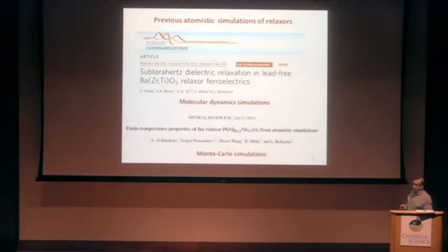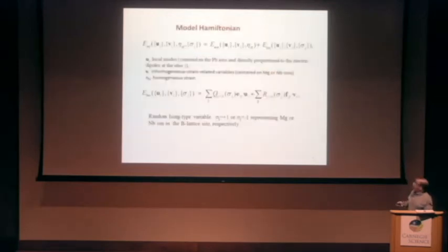We apply the same molecular dynamic technique for PMN. Of course, we need a different model Hamiltonian, and we use the Hamiltonian from this recently published paper for PMN, but they apply Monte Carlo simulations. But the Hamiltonian we used was exactly the same. And this is briefly the review of the approach. It's quite general. We have the Hamiltonian with two contributions, the average contribution, and the second one, local contribution, which is related to the disorder in the arrangement of magnesium and niobium cations over the lattice sites.